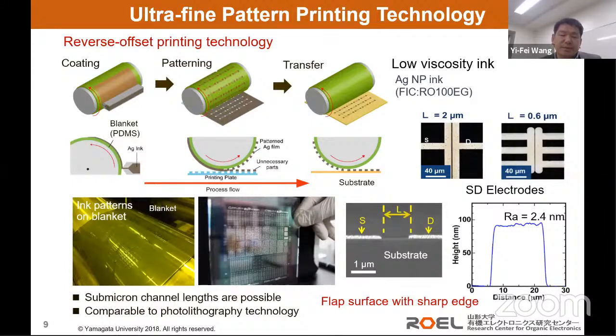And the printing process is shown in here, and we can see firstly the ink was coated on the blanket, and then the ink film was patterned by using the printing plate, and then the remaining pattern on the blanket was transferred onto the target substrate. By using this method, we can achieve very high resolution features of the electrode. And in this page, we can realize the source and drain electrode with a distance as short as 600 nanometer.